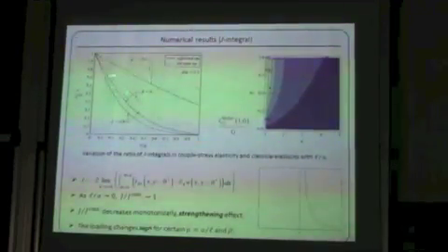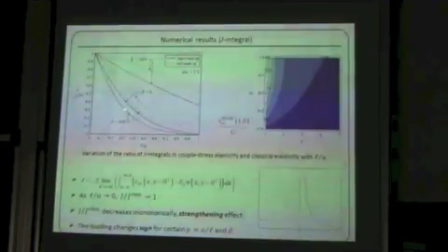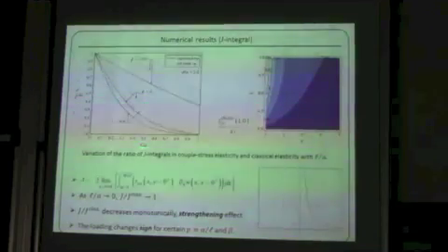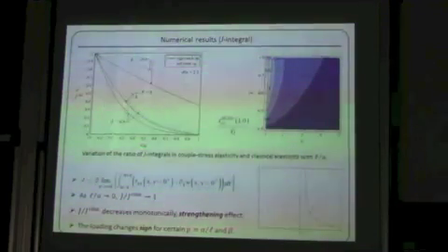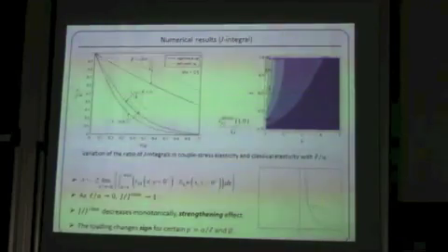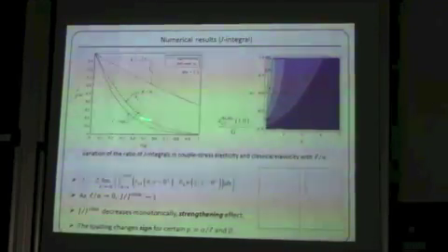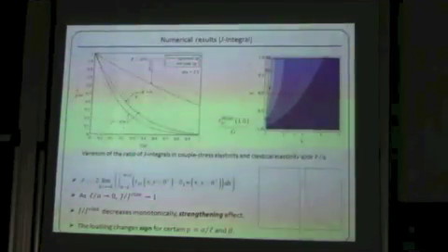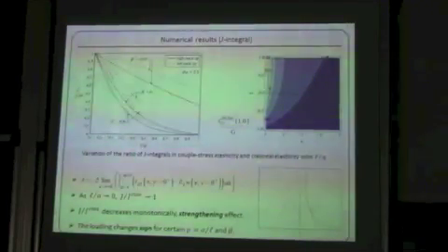Again, we plot the J integral results. In this case, we see that in all range of L over A we are above unity, and thus in the anti-plane problem a strengthening effect is predicted throughout this range of material parameters.